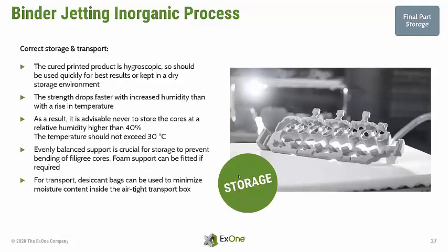The inorganic parts are hygroscopic and finally even water soluble. It is critical to either use the parts soon after printing for the pour or control the environmental conditions during storage and transport. The strength drops with increasing humidity and therefore a relative humidity of 40% and temperature of 30 degrees Celsius should not be exceeded. For storage, it is also recommended to provide evenly balanced support, for example with foams, to avoid bending of fragile parts. For wider distance transport, it is recommended to enclose the parts in airtight plastic with desiccant bags to minimize the moisture content.